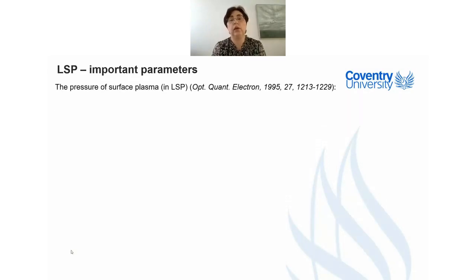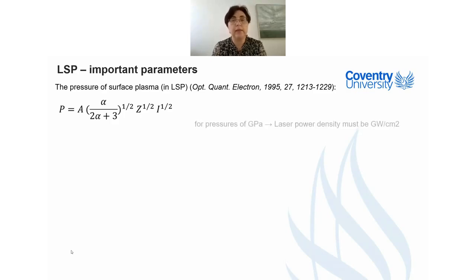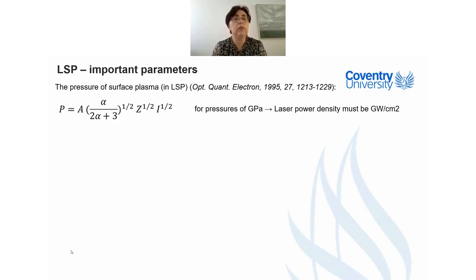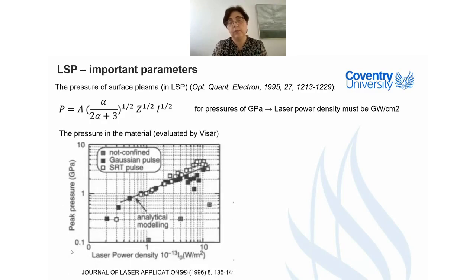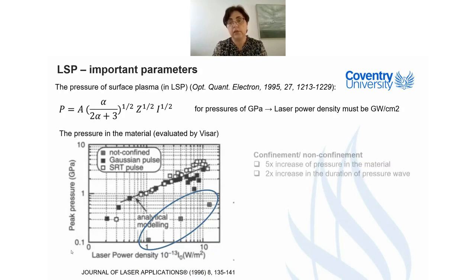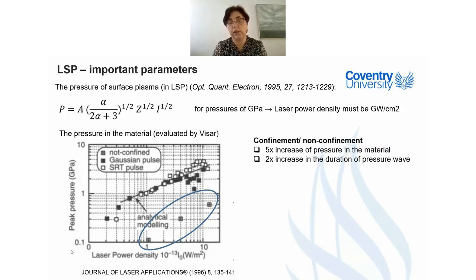So what is happening? We have plasma pressure, which plastically compresses the metal in the normal direction. The metal would like to expand to conserve volume. Then the surrounding metal resists and sets up a compressive field. So now, as you see in my video, by treating the area by moving the laser spot next to each other, you can create residual stress over the treated area.